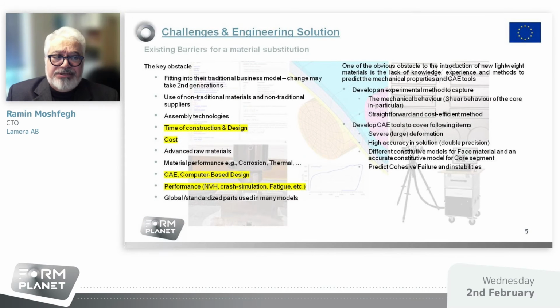And our task here, in order to eliminate all those obstacles, is to develop an experimental method to capture the mechanical properties of the material, especially shear conditions for sandwich material. It needed to be a cost efficient way to make such an experiment. Most of the experimental setups I could find in the literature, at universities and everywhere, were not cost efficient and take so long time to get only the result. So that's not good at all for SMEs.